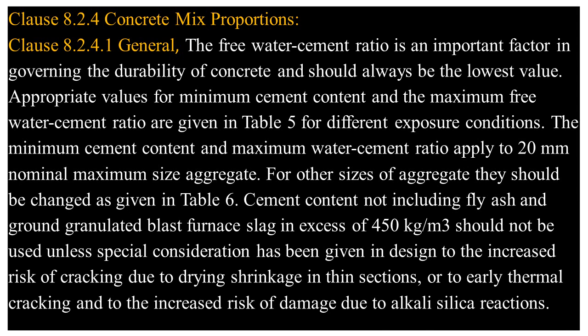Cement content not including fly ash and ground granulated blast furnace slag in excess of 450 kg per cubic meter should not be used unless special consideration has been given in design to the increased risk of cracking due to drying shrinkage in thin sections, or to early thermal cracking and to the increased risk of damage due to alkali-silica reactions.